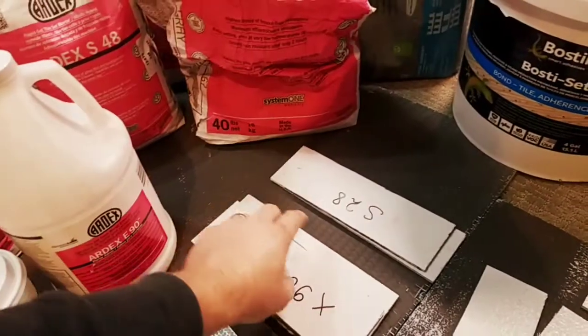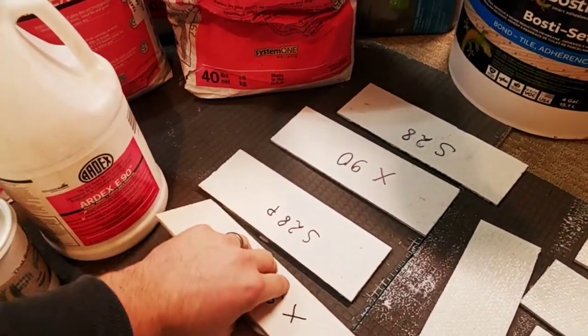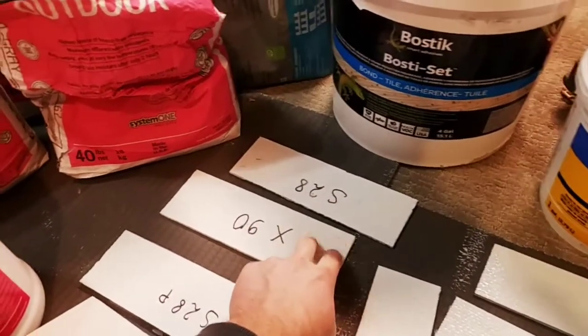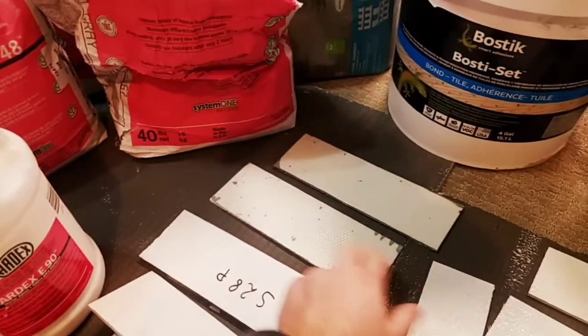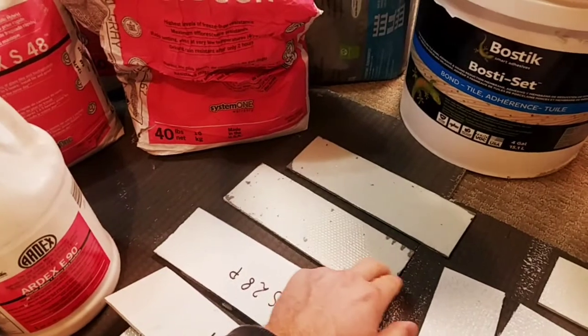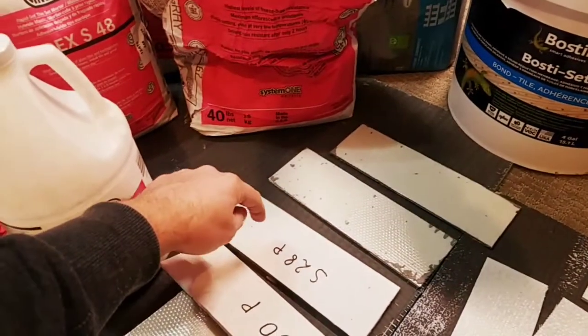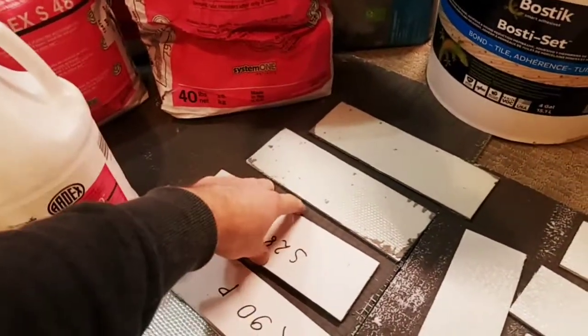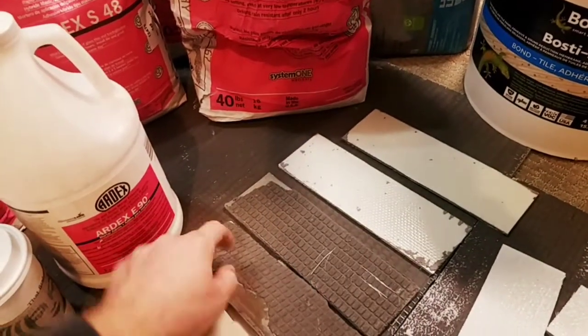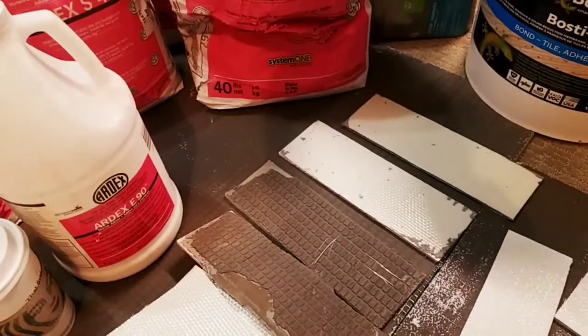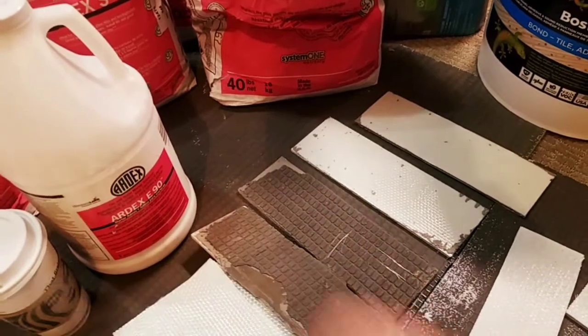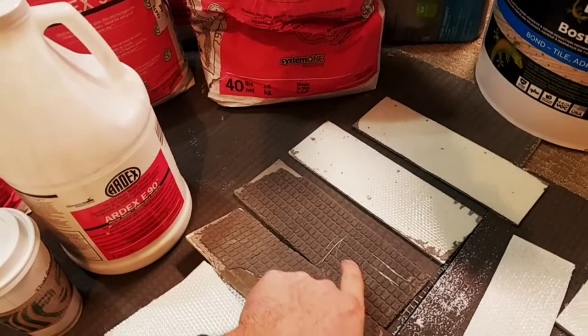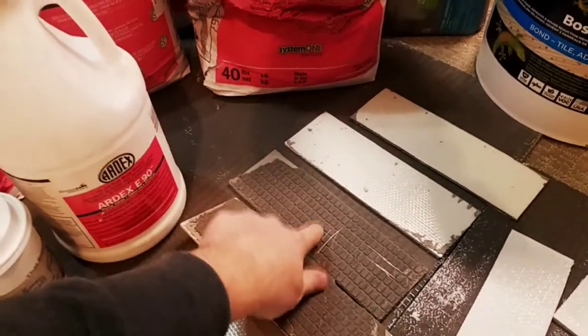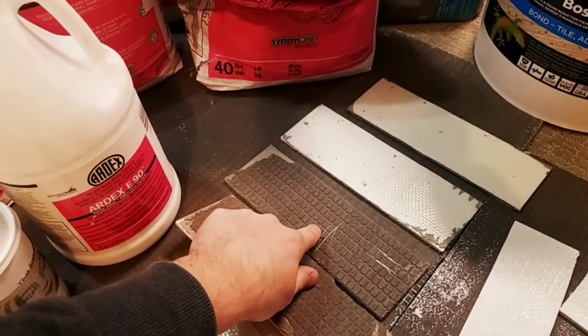So I tested those two mortars with non-primed samples of Dekton Slim, and I also primed two tile samples. The two samples that were not primed, I was able to remove absolutely free of mortar. I used chisel and hammer, and they were removed pretty easily. But when it came to primed pieces installed with the same mortars, they came off tearing out pretty much the Wedi cementitious coating with them. It was installed over Wedi board. So you can see the difference, and this was only a 6 hour test. In 6 hours, this is the bond with primed pieces and not primed.